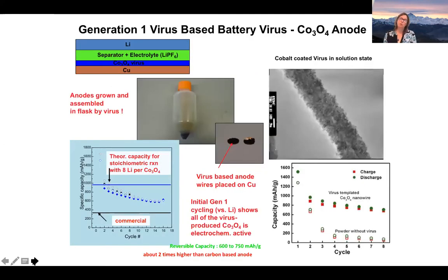So what we did was we grew these electrodes in the lab. This particular picture here is a transmission electron microscopy image of a virus that is nucleated, very tiny. These are less than 4 nanometers, so the size I showed in the beginning schematic of cobalt oxide, all grown in basically a shaker in the lab.